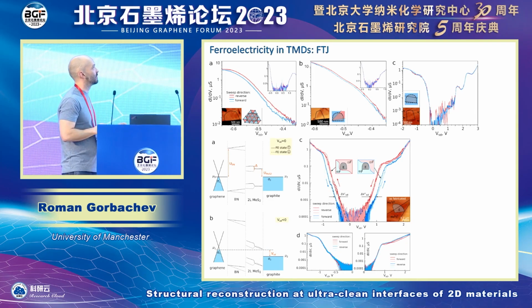So this switching, for example, is more suitable for neuromorphic type devices because it is in essence a resistive switching. And if you have just a single boundary in your tunneling area, when you apply the field, you can completely expel it out of the junction. And that means that you have quite a large offset in your tunneling, and that is more like a classical ferroelectricity. So already by just putting these devices in different place of the twisted lattice, we have different functionality that can be used in a different way.